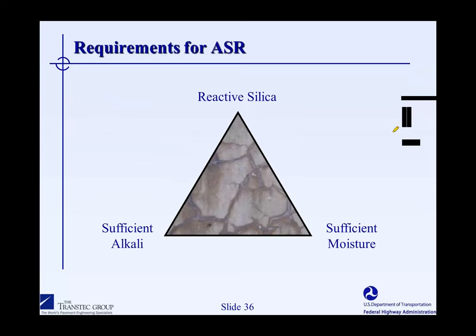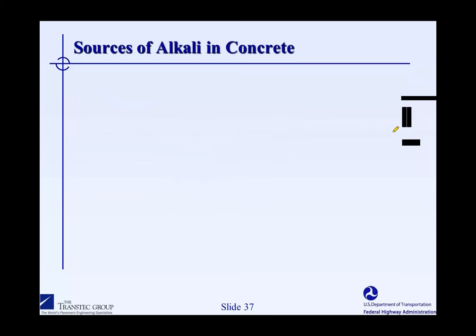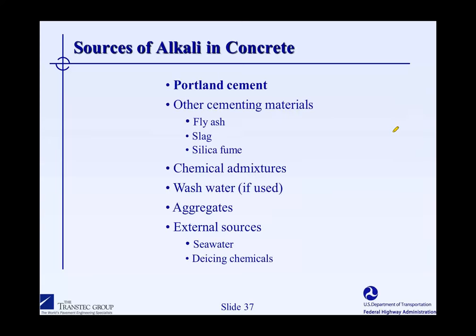Okay, I'll go back to our reactive requirements again: reactive silica, alkali, and moisture. What actually are the sources of alkali in concrete? Well, the main source is Portland cement. Even though the alkali content of Portland cement is generally less than 1%, it's still a major player because those alkalis are soluble.